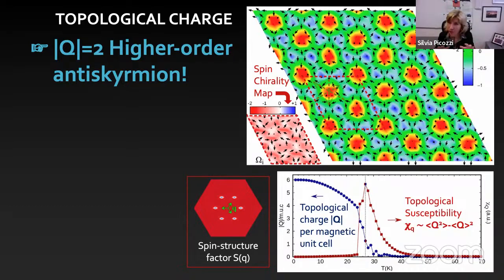So I need a frustrated system, and so this would have a helix, right? But then I need some non-coplanarity, and the non-coplanarity comes from anisotropic exchange. But if I only have anisotropic exchange, then I don't get the anti-skyrmion, at least in the trials we made with sort of realistic parameters. Maybe if you have it very large, maybe you do, but it's not in a realistic range.